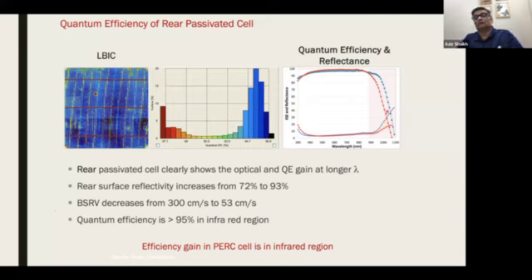And most of the improvement comes in the longer wavelength. And the longer wavelengths are reaching the backside. So most of the time, if you see efficiency improvement in the longer wavelengths, that is from the backside of the solar cell. Okay. And earlier I talked about BSRV decrease from 500 to 100. In this study, they are reporting a decrease of 300 centimeters a second to 53.